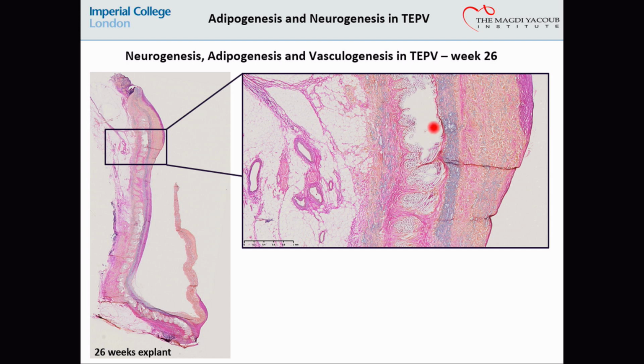The knit, you can see it over here. And the cells, wherever they are homing in from, do seem to really like the knit, because you see there's abundant collagen around the knit, and you can see these bridges going through the knitted scaffold. For some reason, the cells really like the topography of the knitted scaffold. The knitted scaffold was meant to be a support structure, but it actually aids the remodeling of our sinus wall.